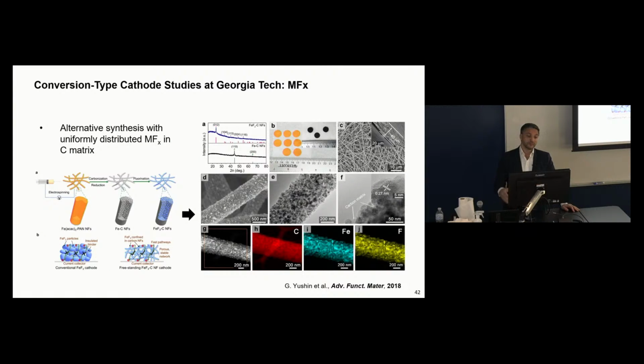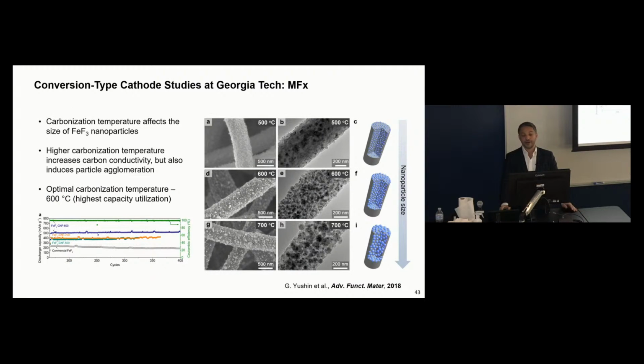You can also use different procedures. You can start with precursors that comprise both the precursor for the carbon scaffold or matrix material and the precursor for the metal fluoride. So in this case, we use nanofibers. We use the electrospinning technique. You can use different techniques to produce spherical particles or particles of whatever shape you want. And again, you can have very high uniformity in these composites, and depending on optimization conditions, you can have high capacity and very stable performance for many, many cycles.